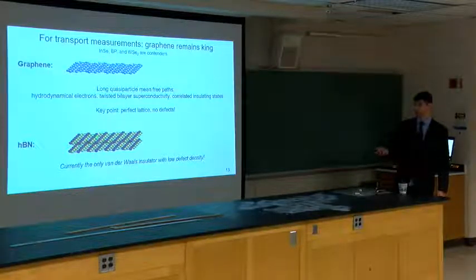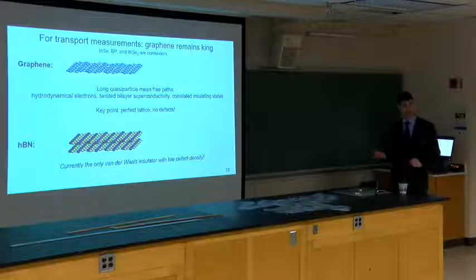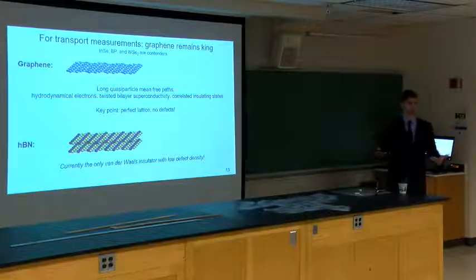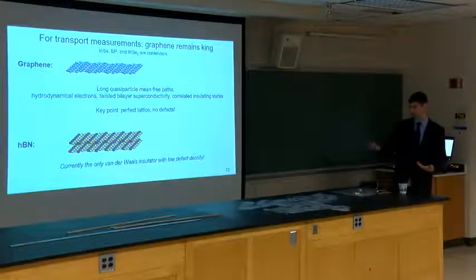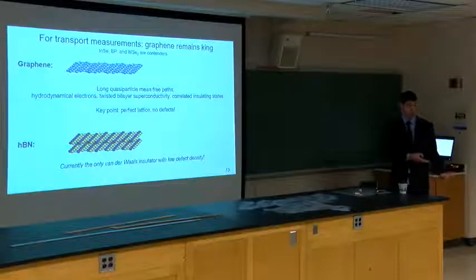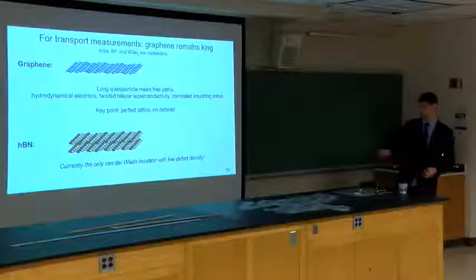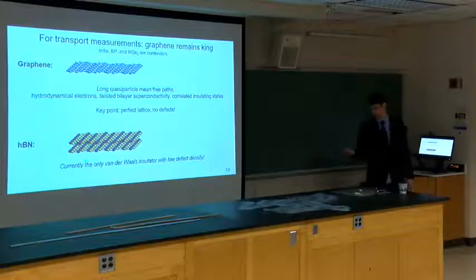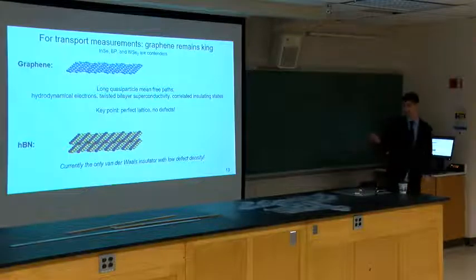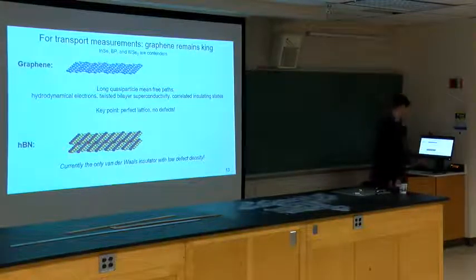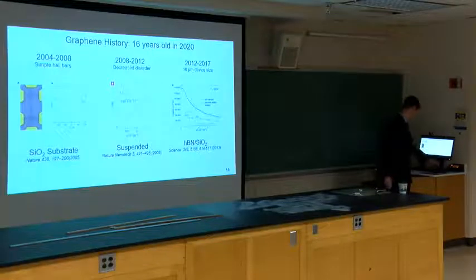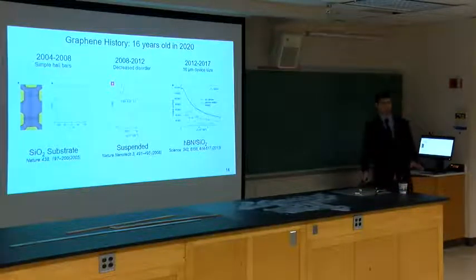The other issue is that you need a very, very perfect insulator, because if you're measuring graphene, you're measuring everything around it. You're measuring the dielectric environment that it's sitting in. And if you surround it by a perfect insulator, you ideally could then measure graphene itself, which is still a challenge. And the only option we have right now for anything that comes close to the quality of graphene is hexagonal boron nitride.